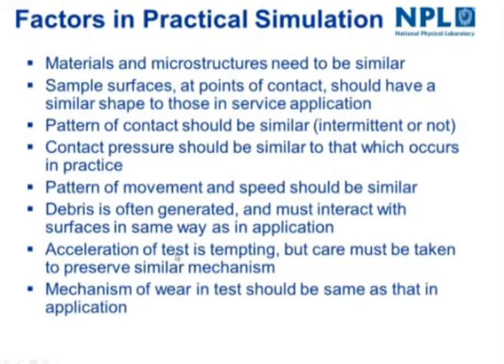The reason it's tempting is that a lot of applications where tribology is important are very long term. Just think about an internal combustion engine and its lifetime of 10 years or so. If you want to replicate wear of that, you can't carry out a test for 10 years. So how do you deal with that? The crucial thing that you always need to make sure is that the mechanism of wear in the test should be the same as that in the application. How do you do that? Well, we'll come on to that, but a very important thing you need to do is to use examination of the surfaces and microscopy and that sort of thing, and we'll come on to that in a moment.